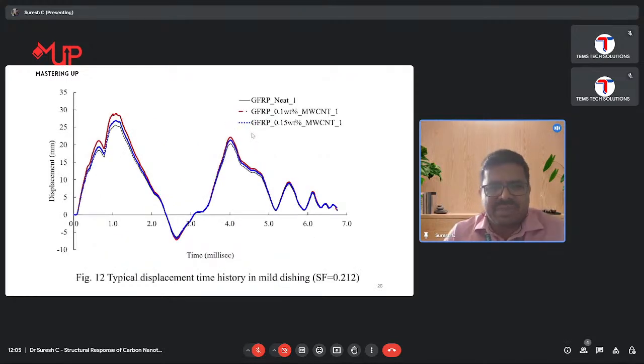And then we have measured the displacement. Whatever we have done in the experiments, we have repeated for numerical simulations. With the same experimental setup, the same way we have done the numerical simulations, and we have measured the displacements of the composite panel, what is the maximum displacement it is going.